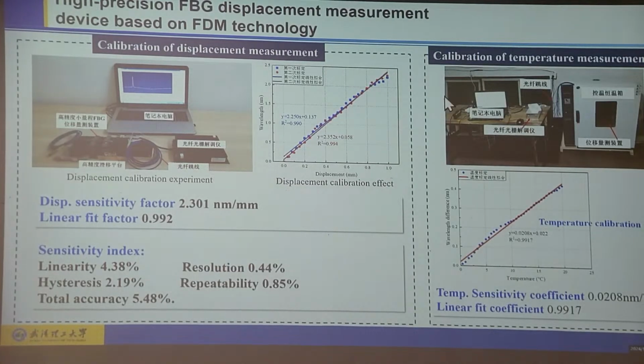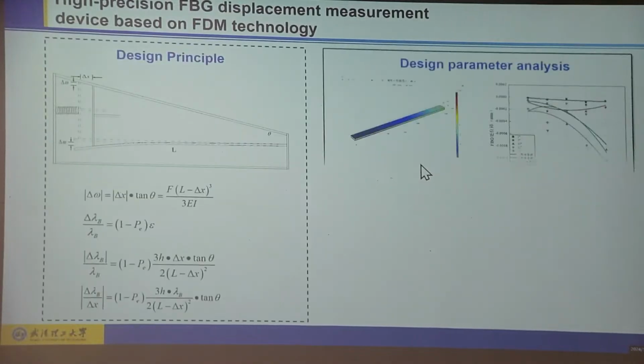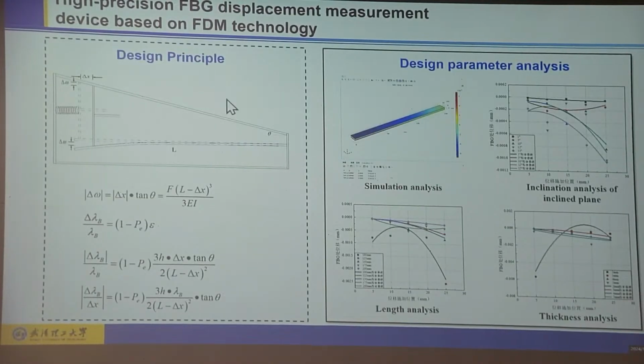We do some calibration tests in this oven. We increase the temperature, and we see the wavelength difference in this temperature calibration test. And also in the same design, we proposed another design principle to measure the deformations, large deformations.